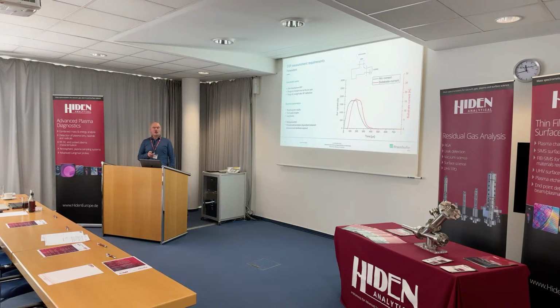This is one measurement of the current itself inside the chamber, this is the exact arc current I showed you before on the slide. It's starting with time 0, and then we have some sample holder here in the chamber after bending of the plasma, of course, 90 degrees, and then we have some ion current. You see the different scale over here, and so we have some time of flight effect, of course, at least 50 microseconds the plasma needs from the starting point to the substrate. And of course, the substrate is always put in with 100 volts bias voltage to avoid electrons coming in.